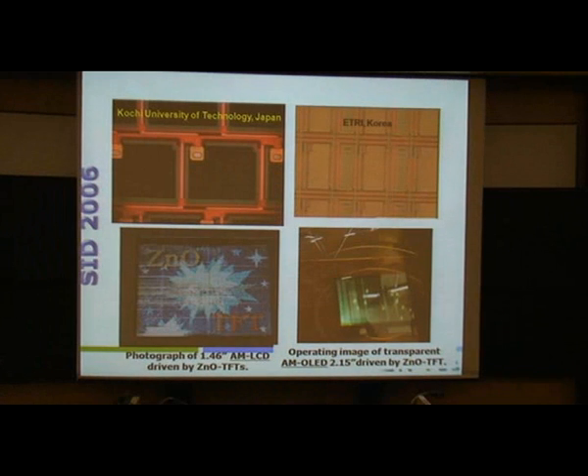So these are some examples, some prototypes that appeared 2 years ago from Kochi in Japan and ETRI in Korea. They present some prototypes using active matrix TFTs based on zinc oxide. Okay, this is a picture. The display doesn't work quite well. We have some defects, but it's working. Even though the diagonal is not too high, 1.46 inches, this one was based on LCD, and this one was based on OLED technology, but both used zinc oxide TFTs.